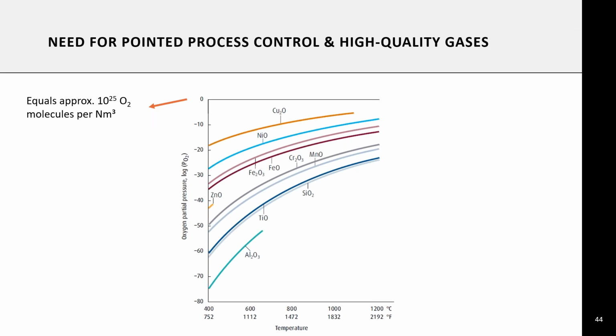Which brings us to one of the last slides here. This is an Ellingham graph, showing the lines of metal to metal oxides at different temperatures and oxygen partial pressures. At any point below the specific line, depending on the material or alloying element, is reducing, and at any point above the line would be oxidizing. So whether you're producing copper, nickel, iron, titanium, or aluminum oxide.